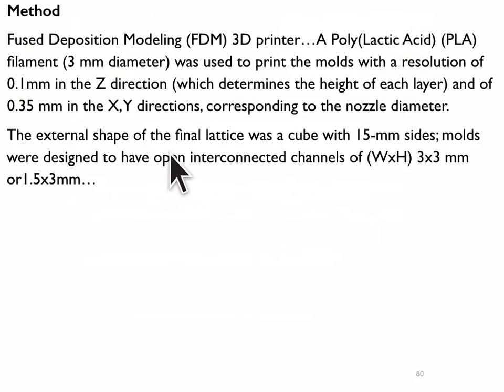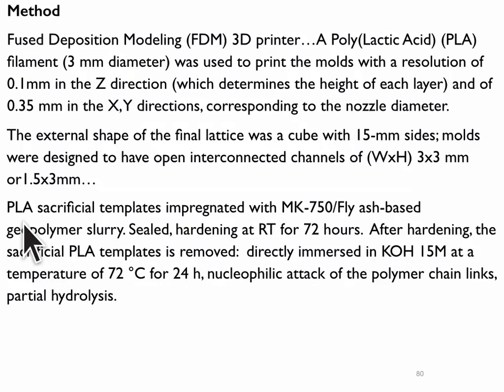The external shape of the final lattice was a cube of 15 millimeter sides. You see, look, this is what we're talking about. Molds were designed to have open interconnected channels. PLA, polylactic acid, sacrificial templates, which means the mold that will be then sacrificed, dissolved afterwards, impregnated with metakaolin-based fly ash geopolymer slurry.